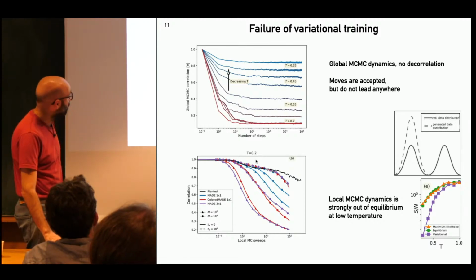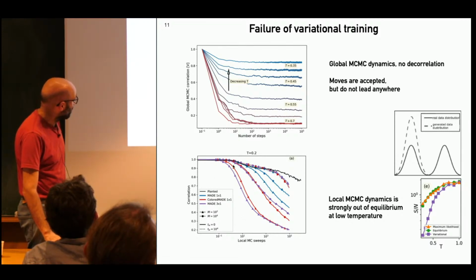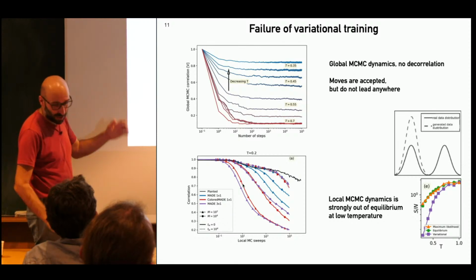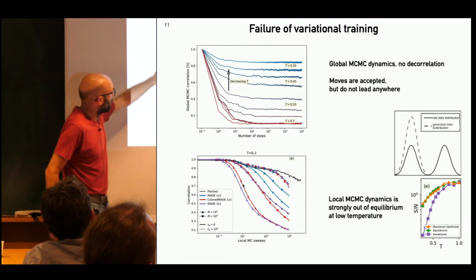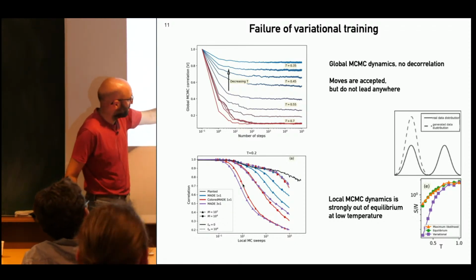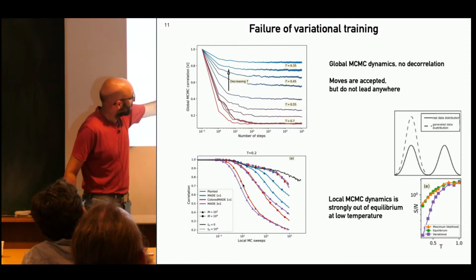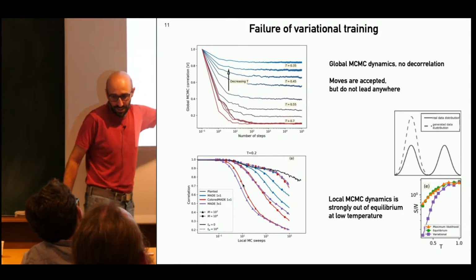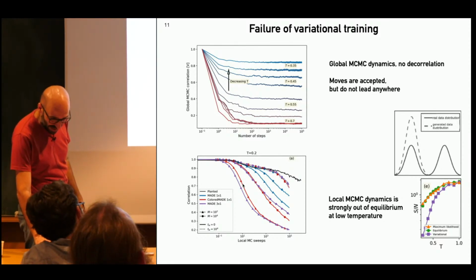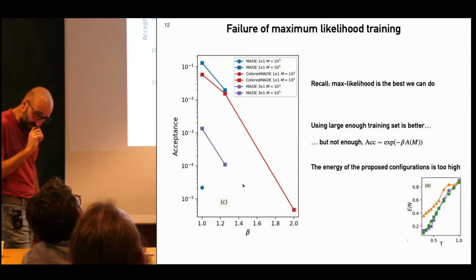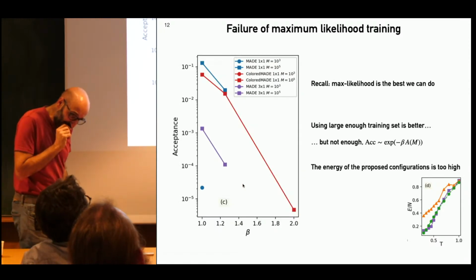At temperature 0.2, unfortunately, the energy starts to become higher, and you start to generate configurations that have a dynamics. This is local dynamics that is faster, and then you see aging, and the dynamics slows down, so you don't gain much. The maximum likelihood has a different problem.